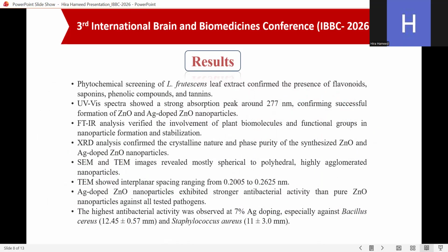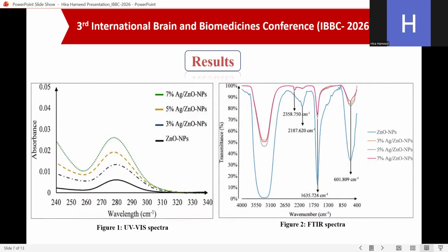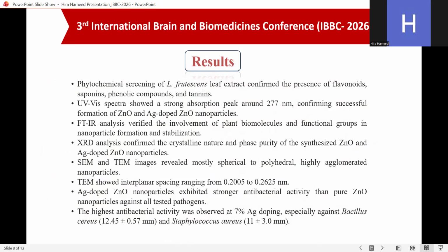Phytochemical screening of the leaf extract confirmed the presence of flavonoids, saponins, phenolic compounds, and tannins. Ultraviolet spectra showed a strong absorption peak around 277 nanometer, as I showed before. Here we can see the maximum peak at 270, confirming successful formation of zinc oxide and silver doped zinc oxide nanoparticles. Further, we did FTIR analysis. This verified the involvement of plant biomolecules and functional groups in nanoparticle formation and stabilization.